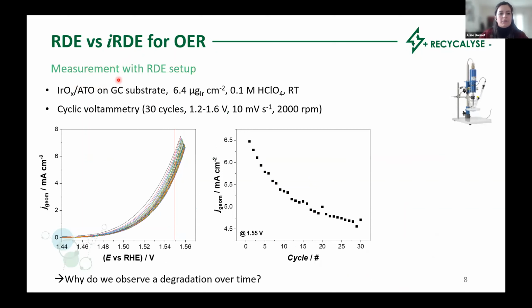So let's start first with the results obtained with the traditional configuration. For that, I casted the ink dispersion onto a glassy carbon, and I cycled it between 1.2 volt and 1.6 volt at 2000 RPM with a scan rate of 10 millivolt per second. And we obtained the current as a response.